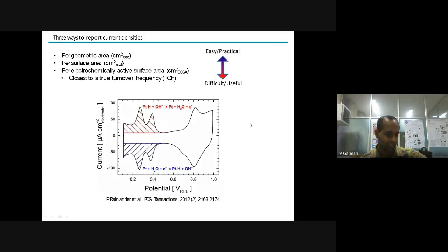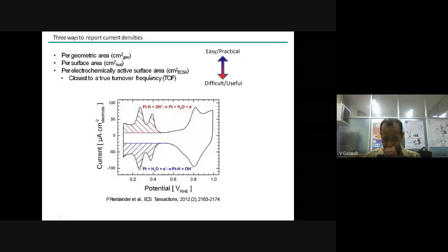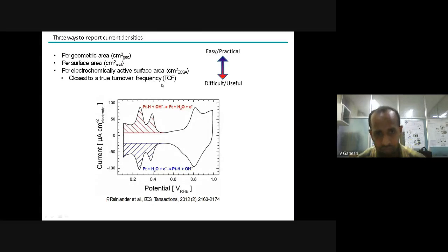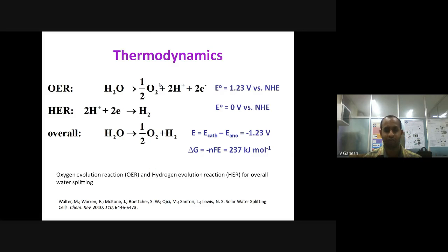How do you measure such electrochemically active surface area? You can use a peak in cyclic voltammetry so that you can directly integrate the peak and measure the charge. What I showed during the discussion of cyclic voltammetry, you can measure the charge under this peak, and you are able to measure the electrochemically active surface area. The closest parameter one can use to determine the activity of the catalyst is turnover frequency. There are formulas one can use to determine this turnover frequency.